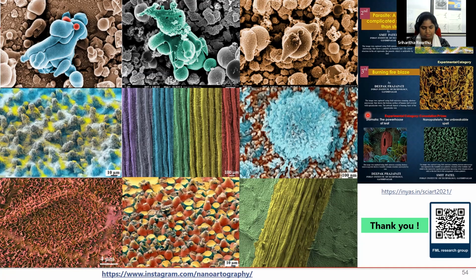Yes, ma'am. And what is the basis for selecting surface active agents, ma'am? If they can reduce the agglomeration by any chance, what is the basis? We look at the zeta potential, right? First of all, you are going to add some of these surfactants, which are also dispersants. When you add a surfactant by some volume, you're going to look at zeta potential. Zeta potential is the surface charge on your particles in the slurry. So a highly negative zeta potential means it is a stable solution.